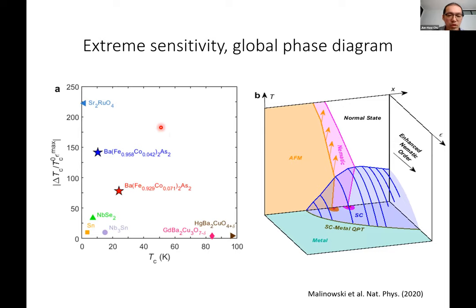I also want to put this into context of how the strain sensitivity compares to other superconductors. So we compile the strain sensitivity, defined by the largest change of Tc divided by Tc achieved by strain, and plot it against Tc for various superconductors. You have two plots here, with some traditional superconductors, tin, niobium-3 tin, and also niobium selenide, and then you also have strontium ruthenate. Basically, the cobalt-doped barium 122 has a strain sensitivity that is above all the other superconductors except for strontium ruthenate. In the case of strontium ruthenate, it's an increase of 1.4 Kelvin to 3 Kelvin, with approximately 0.5% of strain.